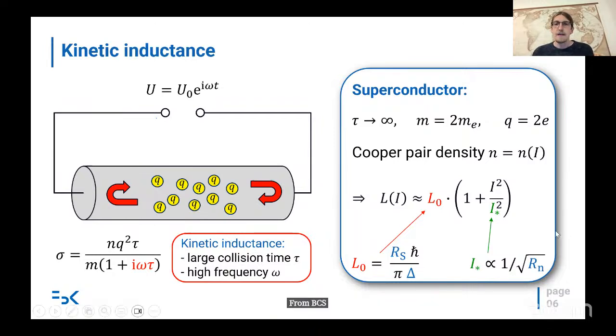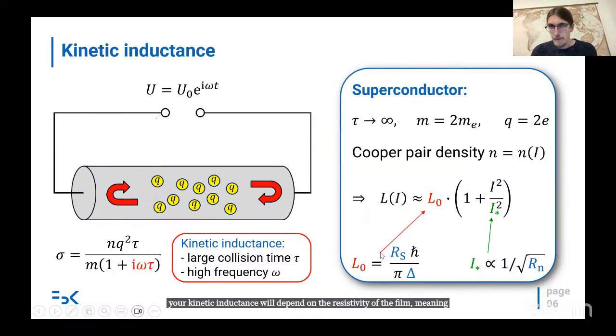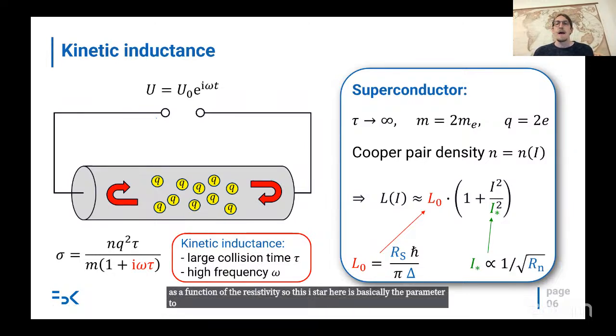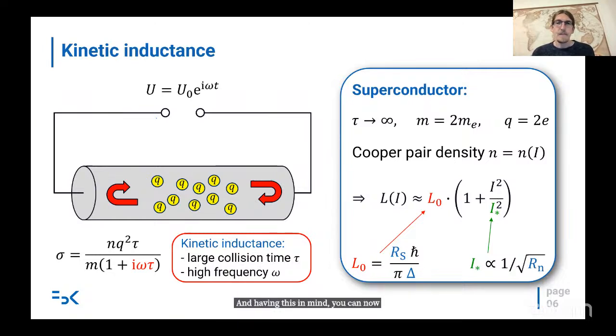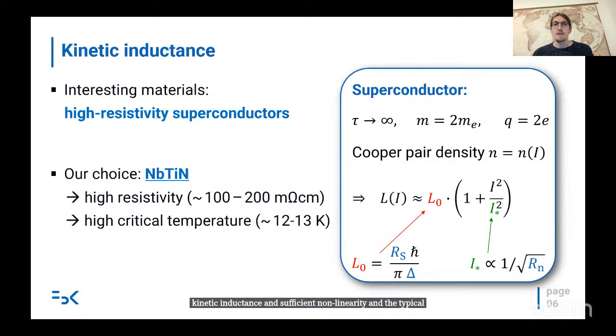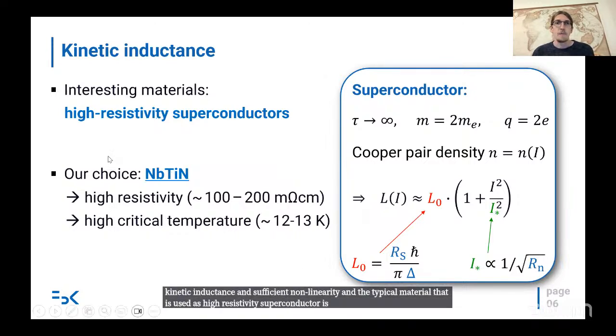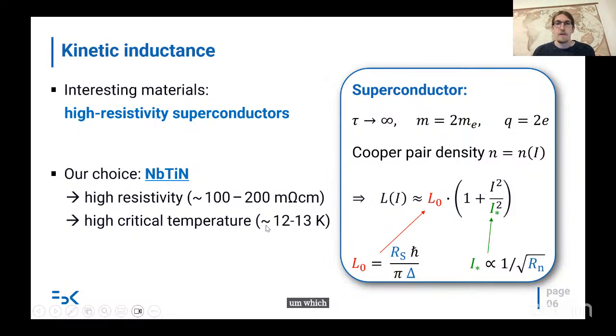From BCS theory, you also see that your kinetic inductance will depend on the resistivity of the film, meaning resistivity obviously above the critical temperature, and also on the superconducting gap delta. Also, your nonlinearity scales as a function of the resistivity. So this I star here is basically the parameter to quantify the nonlinearity. And having this in mind, you can now choose a material that has a high enough resistivity to introduce sufficient kinetic inductance and sufficient nonlinearity. And a typical material that is used as high resistivity superconductor is, for example, maybe NbTiN, which has a critical temperature of around 12 to 13 Kelvin, and which has a resistivity in the order of some 100 milliohm centimeters.